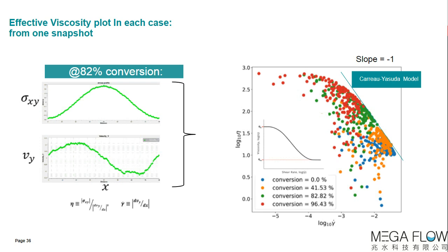What you saw in the Kevlar, as conversion went on, we only showed the video, but for each snapshot in that, you would be able to do that. And this is what we have done here in the PUR case, the polyurethane case. So we have now as a function of conversion the blue, the orange, the green, and then the red. On the horizontal, we have the log of the shear rate, and here the log of the effective viscosity. You see that as a function of conversion, the viscosity goes sky high, which we expect. It is also what happens here because this forms a network that the elasticity also changes a lot. I'm not going to talk about that here today because that would mean a different webinar altogether. But it is very interesting to be able to calculate that too.